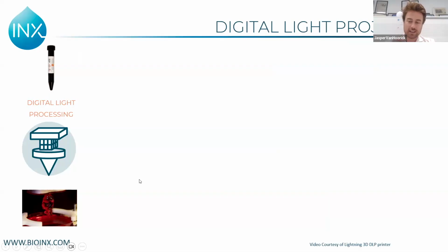Video is not working. So basically how this technology works is you have a light source, then you have a digital micromirror device, which is an array of many small mirrors. Every mirror is 1 pixel, and you basically shine your light onto a container of resin. Everywhere that the resin is irradiated, it will solidify, it will cure, and everywhere where it's not, it will stay liquid. And this is how you can print something in a layer by layer fashion. So you print 1 layer, then you move your build platform upwards, you irradiate the next layer, and that's how you get